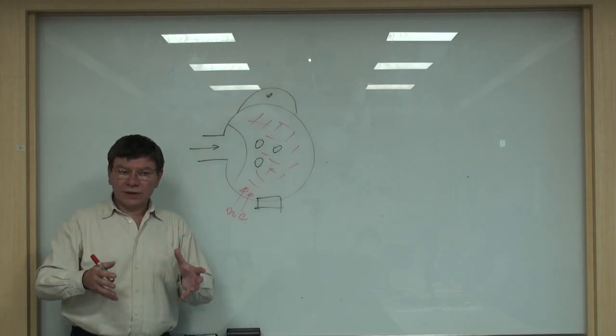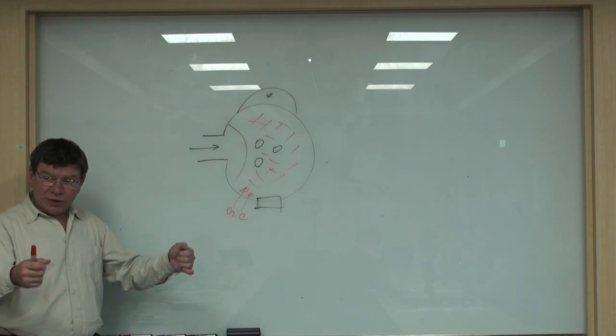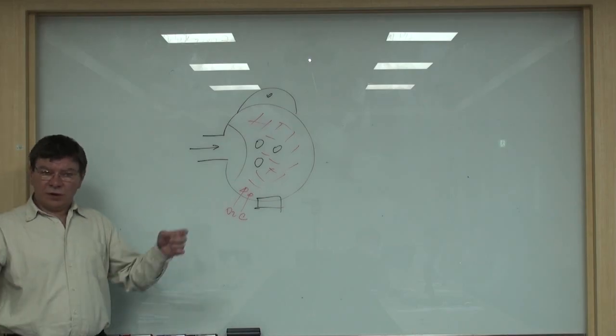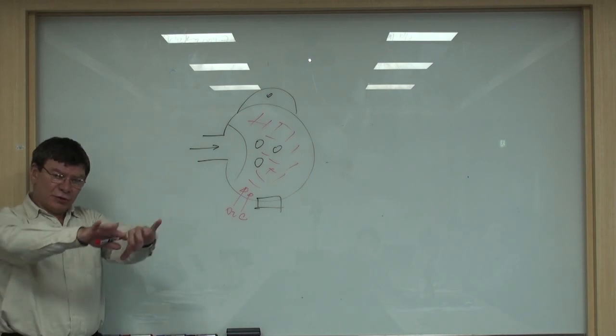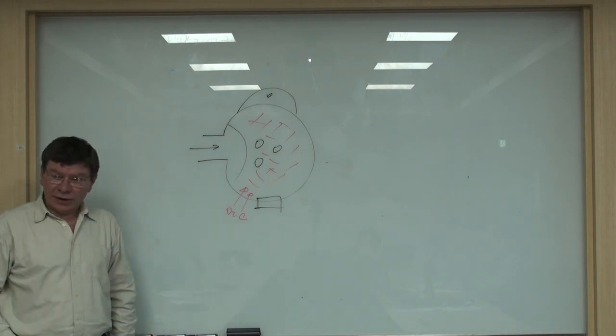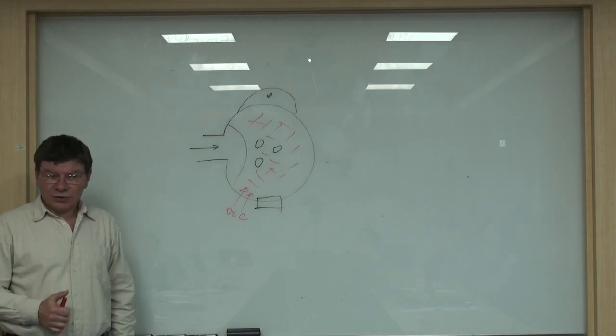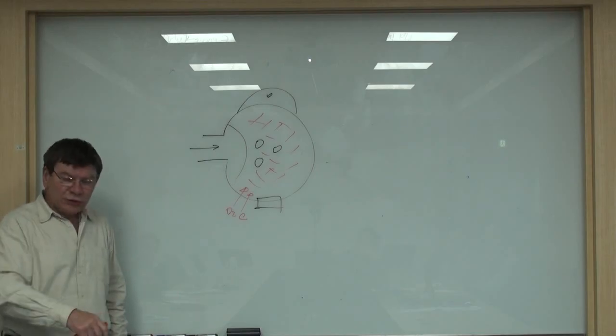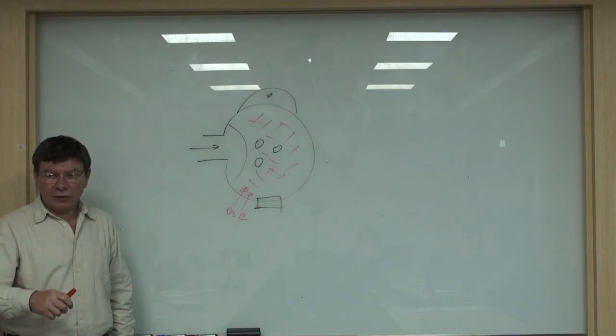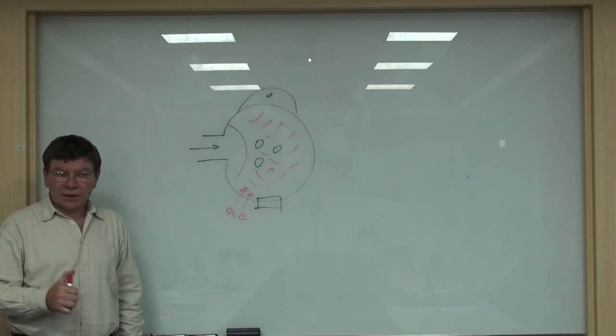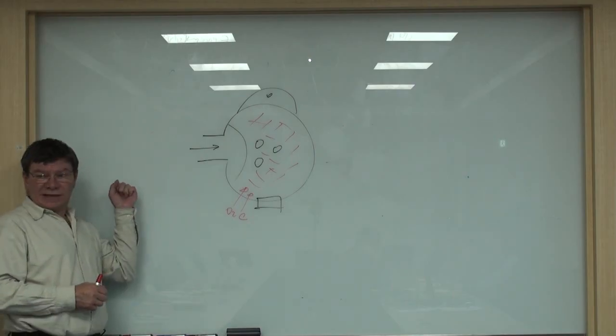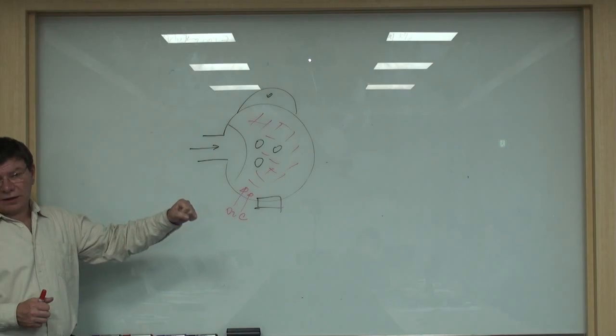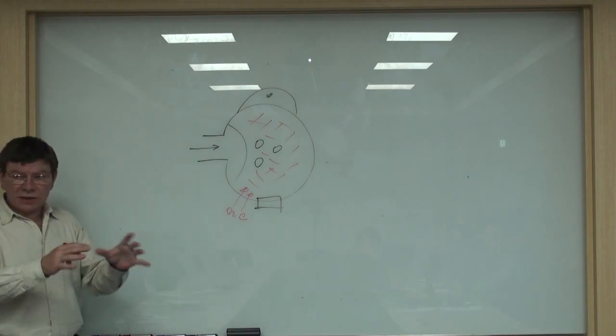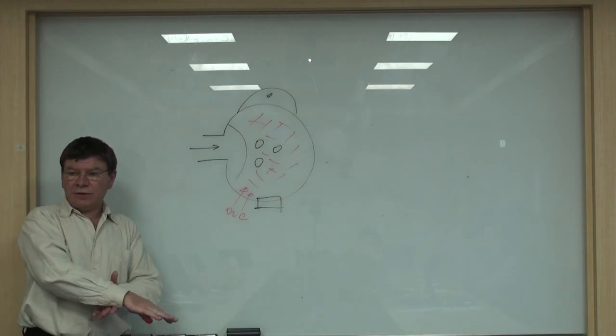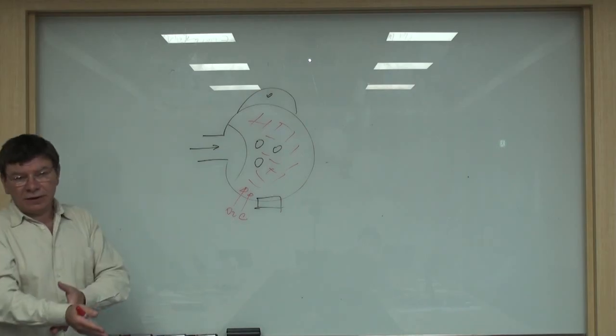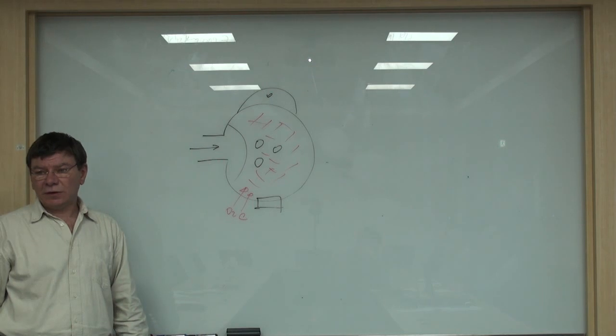As in a conventional furnace, there is no access at the beginning for carbon injection. Even if you inject carbon by the door, the carbon is burnt on the surface and by the air ingress. It surely contributes to the thermal balance, but not to the oxygen equilibrium down below. So that's why the early slag in the conventional furnace is high FeO, but as soon as the slag is accessible to carbon injection, you can reduce the FeO of the slag, and at the end you have even less than 20% FeO in the slag.